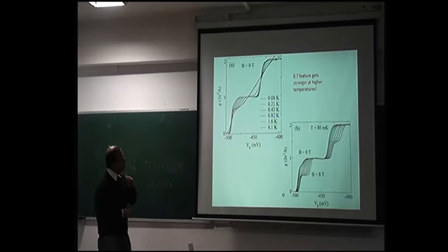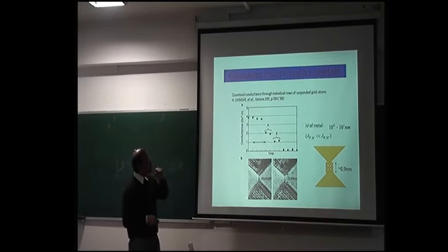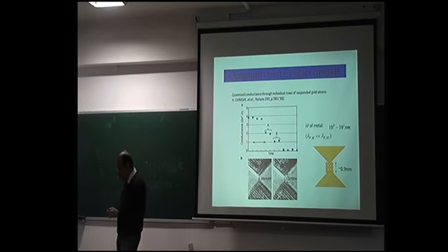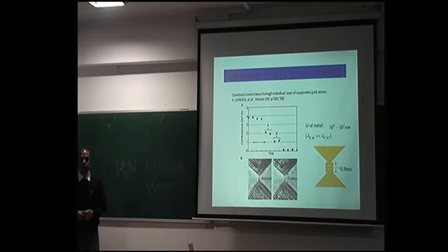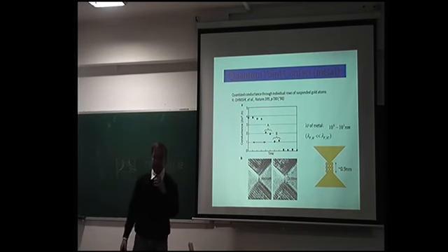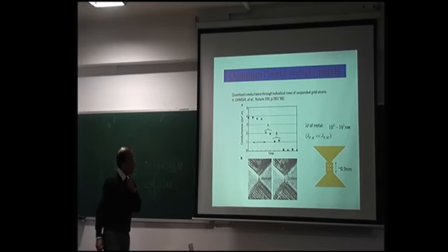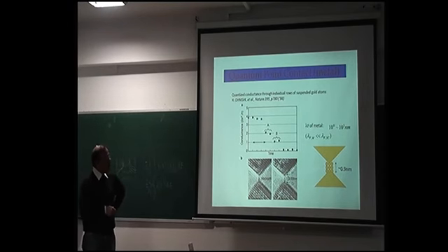Then the next experiment. This was 88, and then it took a long time to observe mesoscopic phenomena or conductance quantization in metal. The reason is that the Fermi wavelength in metal is really low. But finally this Japanese group, in this beautiful paper, showed that one can indeed observe conductance quantization in a metallic nanowire. But whenever they passed a current, the fusing effect used to happen.